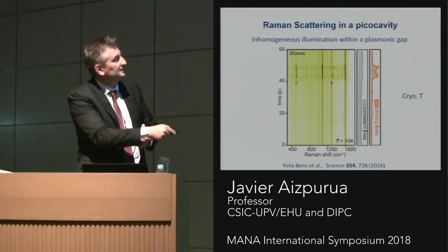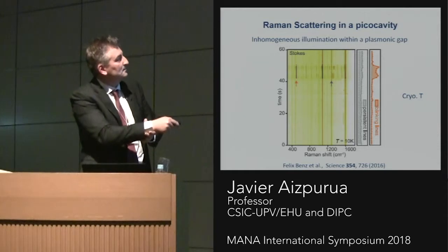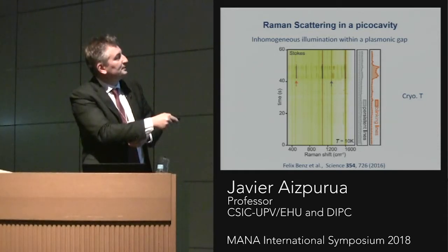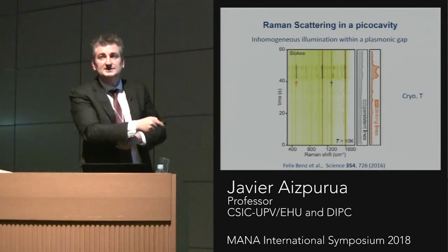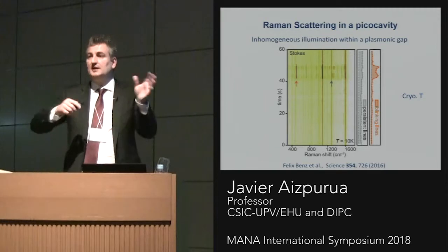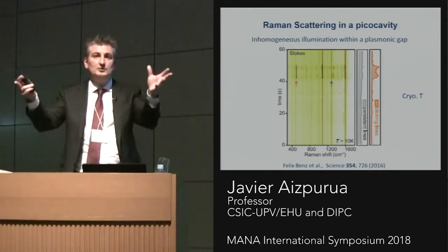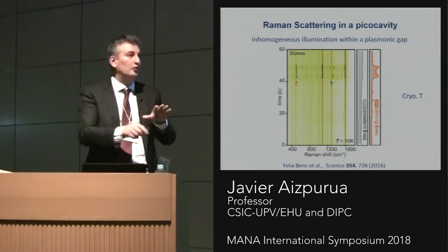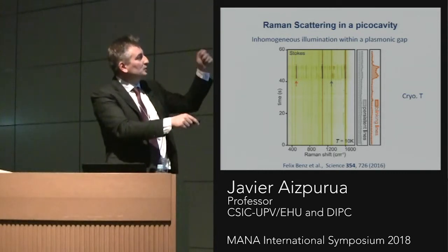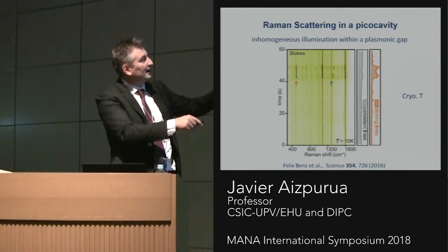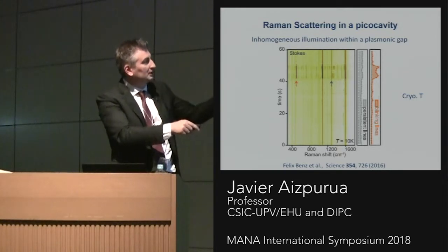Persistent lines here all the time, and then at some point in the spectrum, these non-persistent blinking lines emerge. And these are not typical blinking lines of Raman that are moving around, like everybody who does Raman can identify. This is at cryogenic temperature, very controlled, and even with control experiments, when you turn off the light, you turn it on after several seconds, and it's still there. So it's a very morphological thing, right?